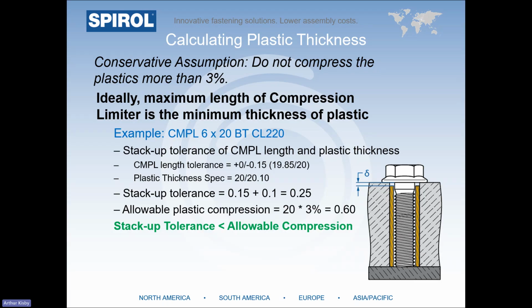In this example, we know that the length of the compression limiter is +0 minus 0.15 millimeters. And since we want the minimum plastic thickness to be 20 millimeters, which is the sealing length of the compression limiter, we want a positive tolerance on the plastic. In this example, we're assuming that the molder can maintain a 0.1 millimeter tolerance. So knowing this, we can calculate the stack-up tolerance of 0.15 millimeters plus the 0.1 millimeters equaling 0.25 millimeters.